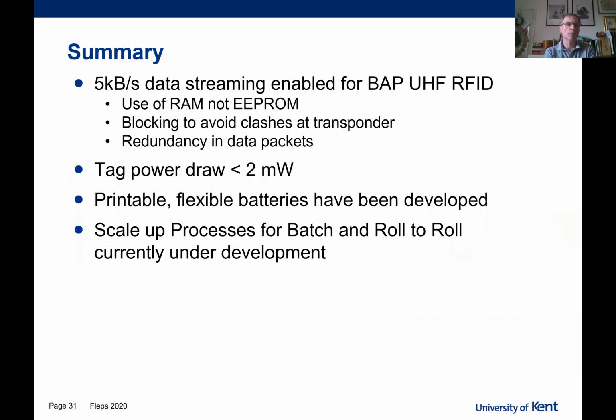So finally, just to summarize, we've achieved 5 kilobytes data streaming using a BAP assisted UHF RFID system. We managed to achieve this data rate by using RAM in the tag transponder rather than the usual EEPROM. We used blocking to avoid clashes and data loss at the transponder. And redundancy in the packets allowed us to improve the transit rate quite effectively and achieve the 5 kilobytes per second. Tag power draw is less than 2 milliwatts, giving us in excess of 100 hours of operation using the coin cell. We've incorporated printable and flexible batteries, which have been developed at the University of Kent. And we're about to embark on a scale-up process for batch and roll-to-roll. This is just currently under development and will be presented at a later date.